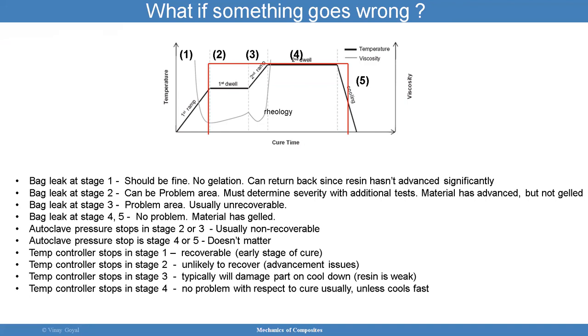In consolidating, if the temp controller stops in stage one, you can recover that. If the temp controller stops in stage two, it's unlikely you can recover, because now again, you have some amount of cross-linking. In stage three, it will damage the part.